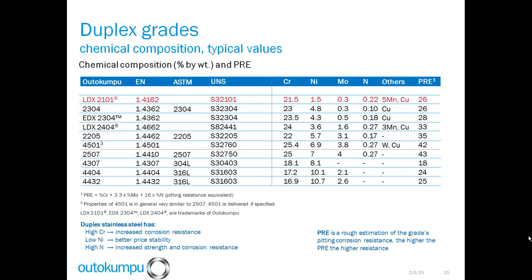Duplex grade compositions are compared to the standard austenitic compositions 304 and 316L near the bottom of this table. What you can see is duplexes have higher chromium and nitrogen contents, but lower nickel contents than 300 series stainless steel. The lower nickel contents result in a more cost-effective alloy.